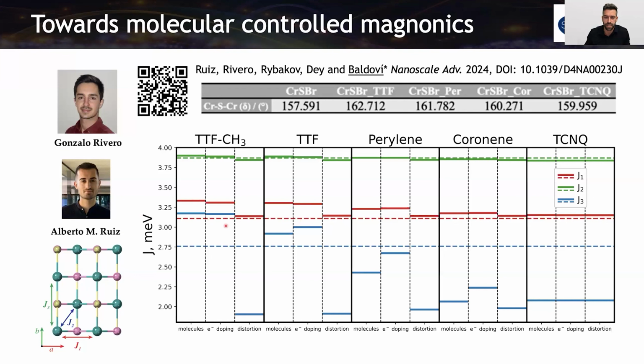We can now test if we just take a unit cell of chromium sulfur bromide and we add a gating, like we are simulating this charge transfer just in the unit cell, we can obtain pretty reasonable exchange interactions. This is the J1, J2, and J3. The red is J1, then we have here J2 and J3, and we can observe that they are pretty close. So the main effect to tune this exchange interaction, the magnetism, is due to the charge transfer.